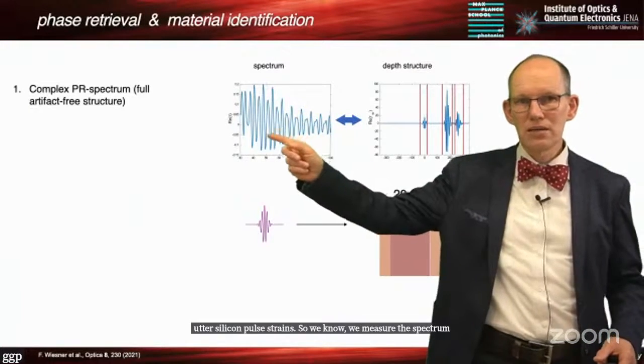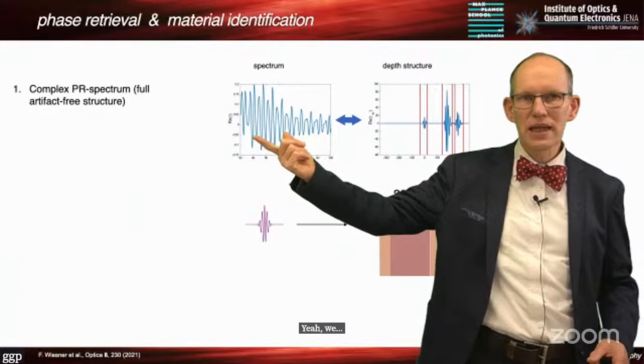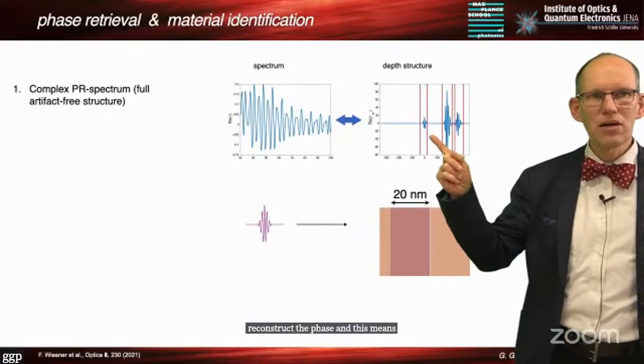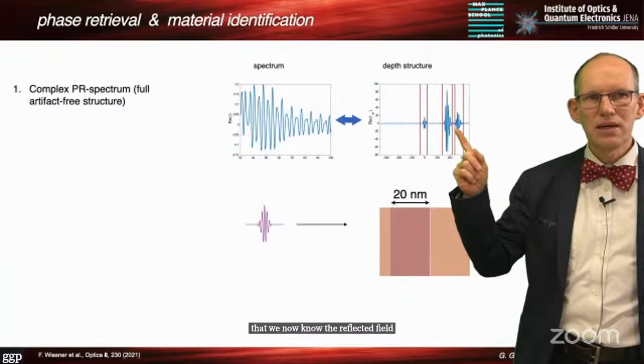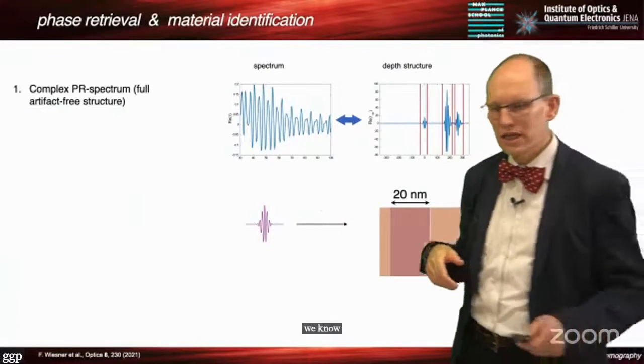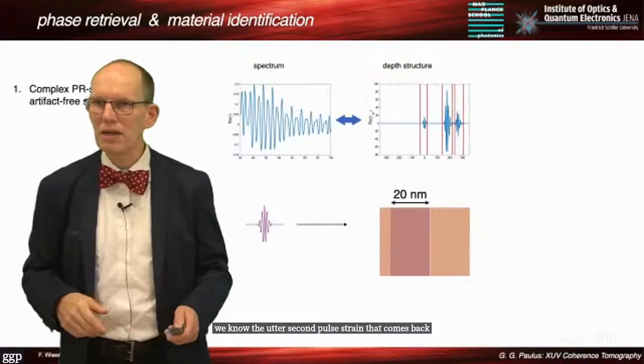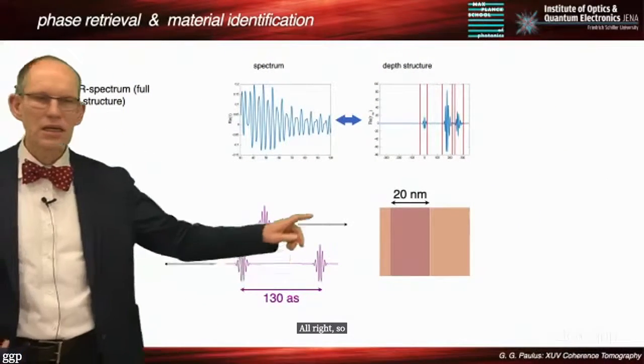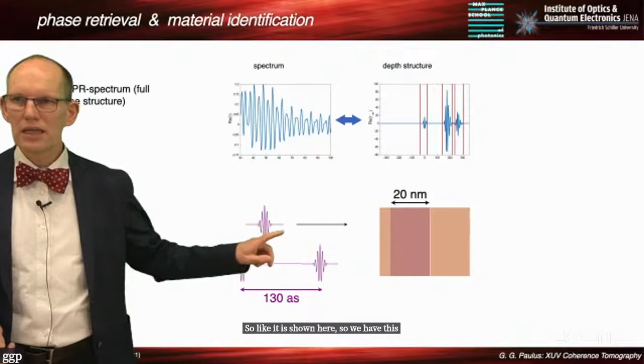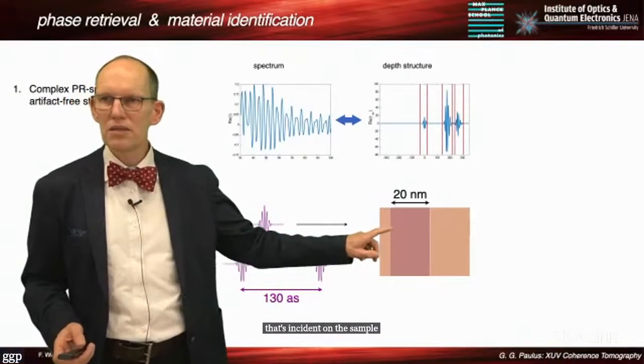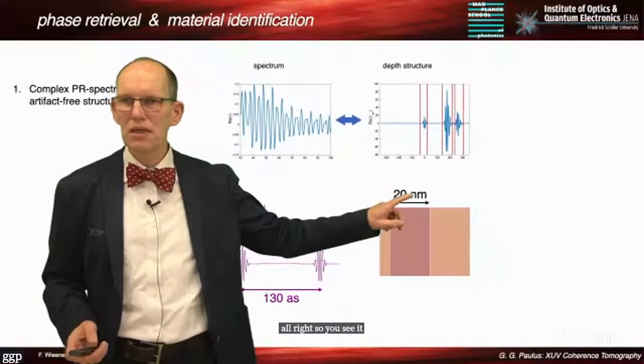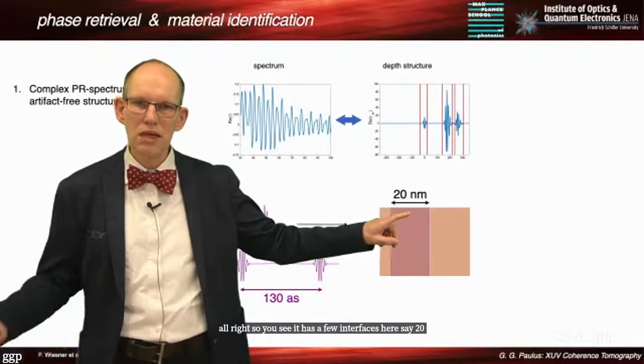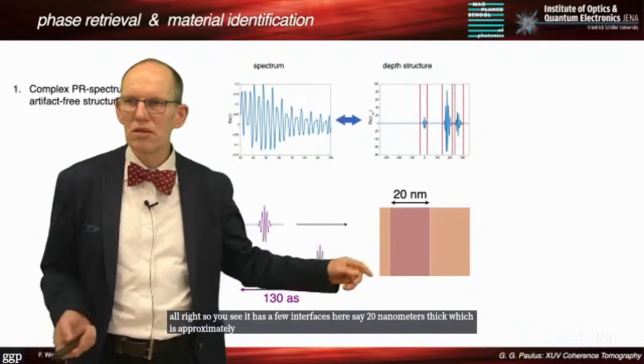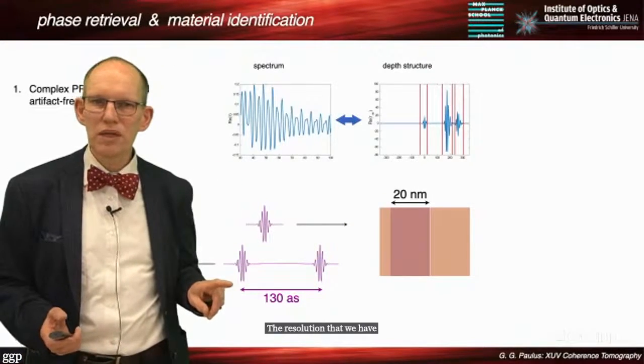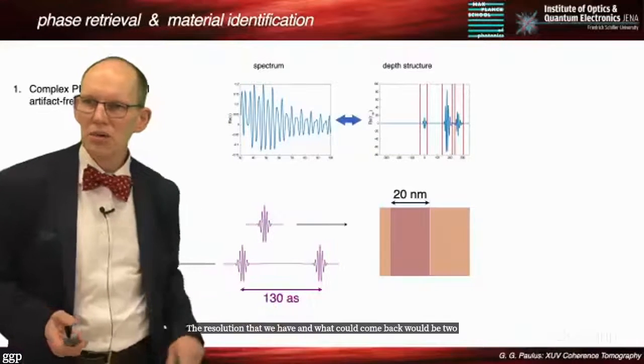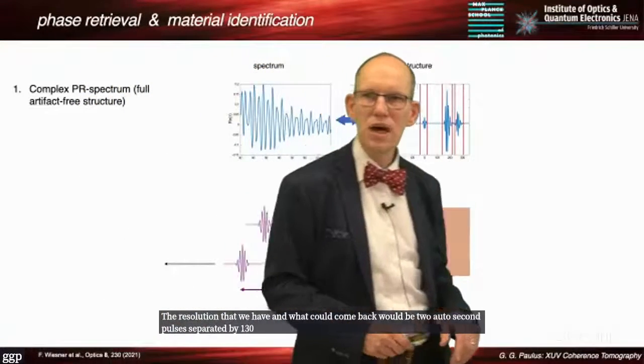So we measure the spectrum, we reconstruct the phase. And this means that we now know the reflected field. We know the attosecond pulse train that comes back from the sample, right? Like it is shown here, we have this pulse that's incident on the sample. You see it has a few interfaces here, say 20 nanometers thick, which is approximately the resolution that we have. And what could come back would be two attosecond pulses separated by 130 attoseconds.